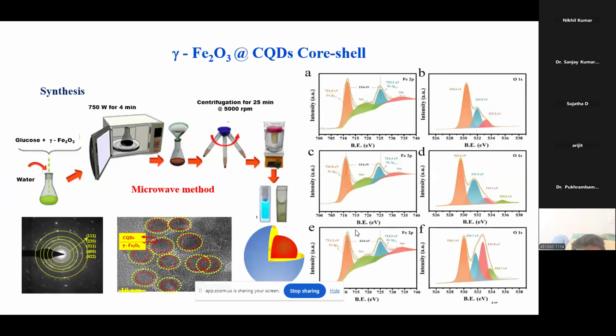Then another work is gamma Fe2O3 at CQD core shell. It's a core shell structure. Usually CQD is below 10 nanometer. This gamma Fe2O3 is one of the iron oxides whose size we cannot constrain. But if we make it with this microwave method into the CQD, it gets trapped at about 5 to 6 nanometer, and the outer shell becomes the CQD. So we can control its size. It can be applicable for sensing applications, and we can use it for MRI, since it is a magnetic particle. We can also utilize it for drug medicines.